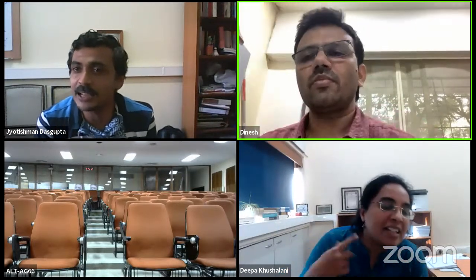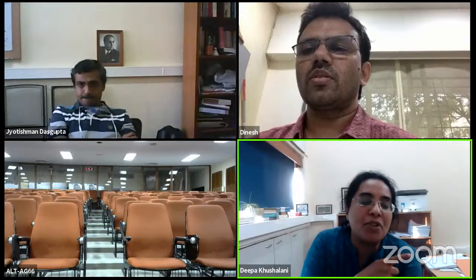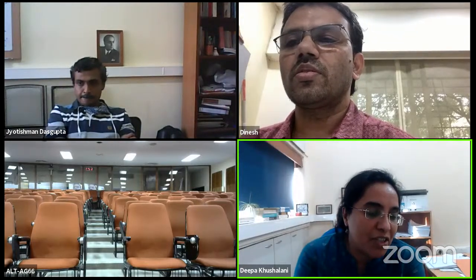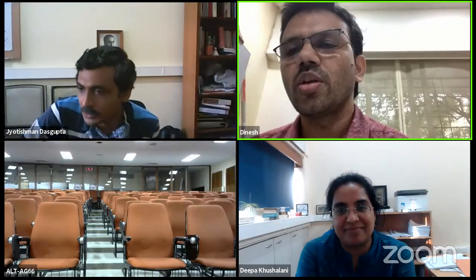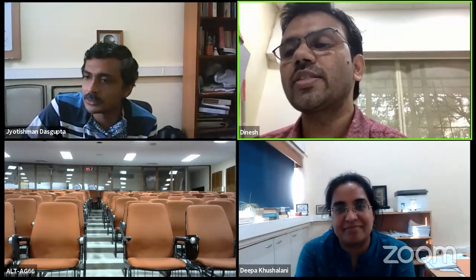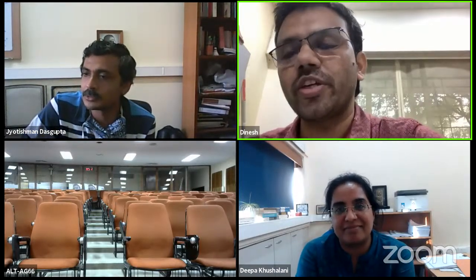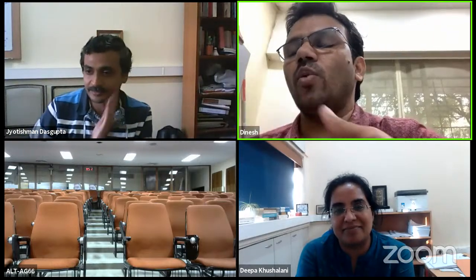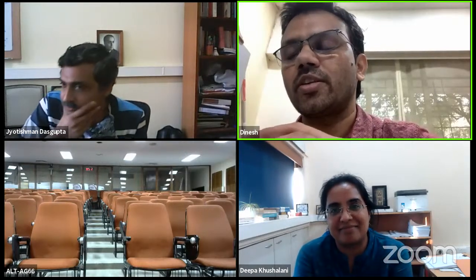Yeah. And the other thing is you don't talk about your VOC, because in both the cases that you showed, yes, your efficiencies and fill factors are good, but your VOC is decreasing when you are putting this. Yeah, because you have the different electronic charge transfer band gap has reduced, and in the pure fluorine case you have the LUMO offset which is different. But overall, if you see the change in the fill factor, our devices are at 12-13%, and one device we have got up to 14 plus. But